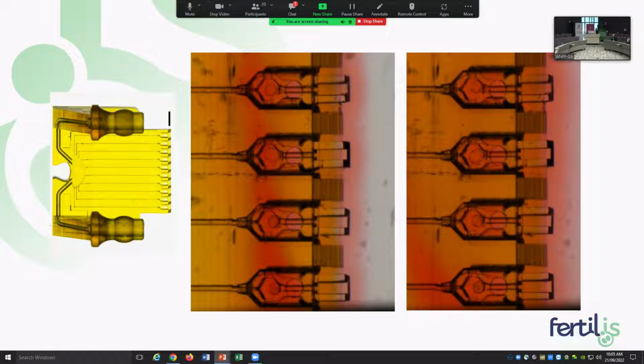Few specs on the nest. So the nest was printed in vat mode again, but this time with a 10 times objective and an air immersion medium. We were using UpNano's high-performance polymer UpPhoto and laser power setting ranges between 50 and 100 milliwatts. Adaptive resolution printing mode was used, which achieved 4 hours and 31 minutes for one complete fully cured part.